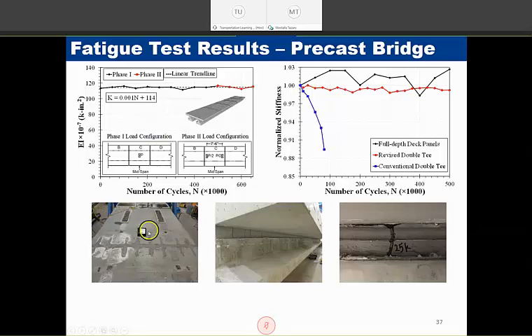Here is the damage of the fully precast bridge during the fatigue testing. We have seen basically shrinkage cracking around all of the cold joints. We also have seen these kinds of cracks on the haunch region. And for one of those open pockets that we filled last, we also saw a water leak underneath the bridge at 25,000 load cycles, which was around 12 years, if I'm not wrong. And we've been monitoring this joint, and it was very interesting because as the load cycle number went up, this joint basically closed, and we did not see any further deterioration of this joint.